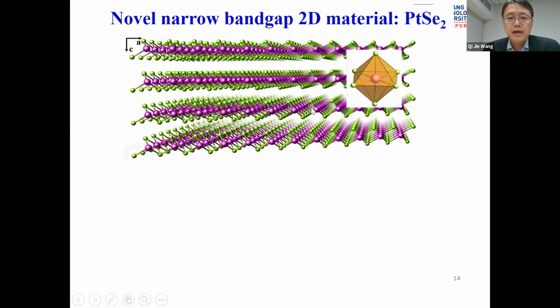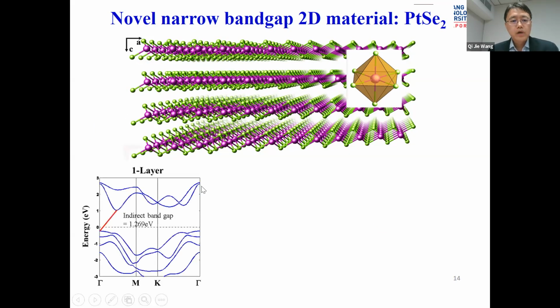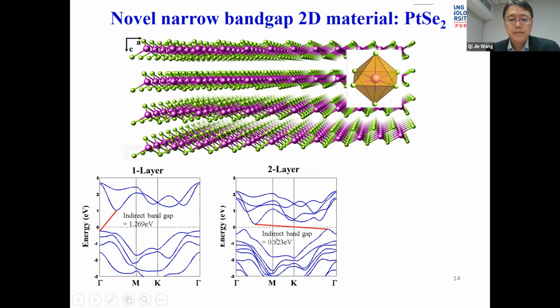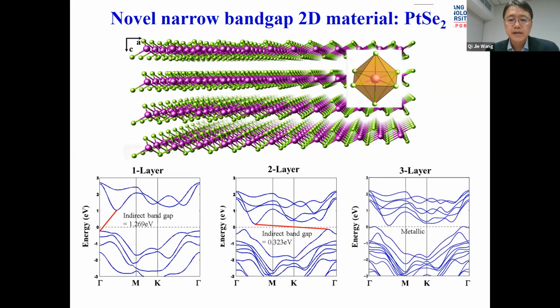This PtSe2 is similar to other transition metal chalcogenide materials like MoS2. Through first principle calculation, we found that monolayer PtSe2 has a bandgap of about 1.2 eV, which is close to the near infrared. The two-layer material produces an indirect bandgap of about 0.3 eV, which corresponds to a wavelength of about 4 micron. The three-layer or thicker material is basically a semi-metal with zero bandgap. Therefore, we should use two layers of such material for mid-infrared applications.